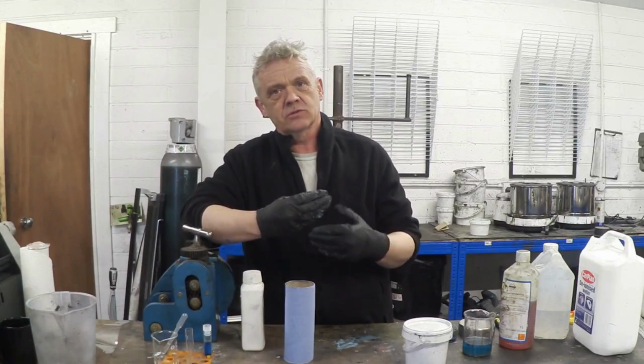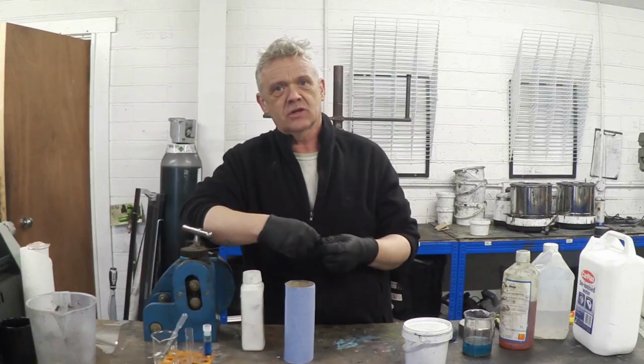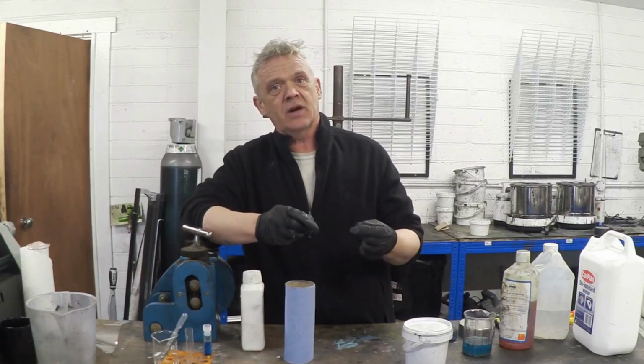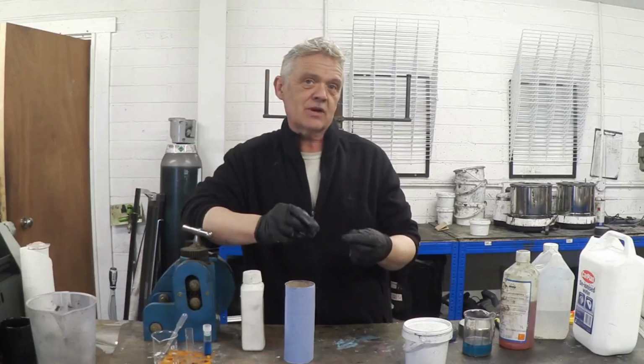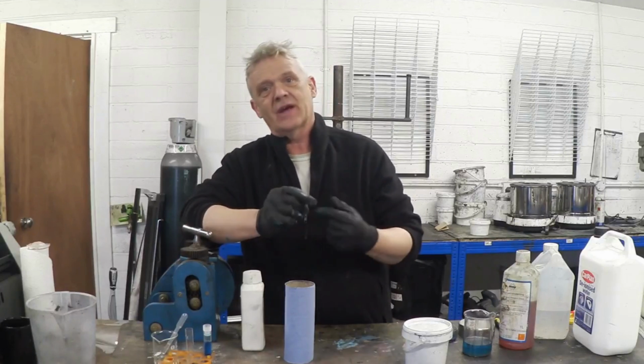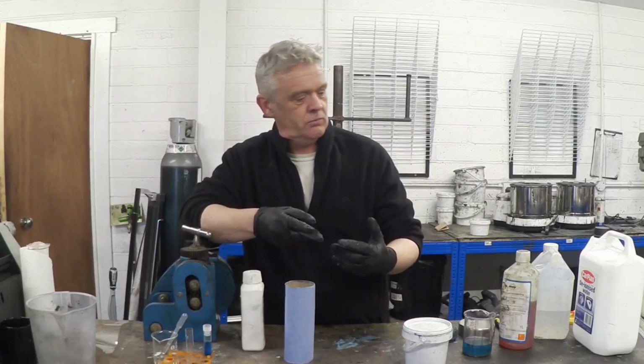Mix it with some graphite or some carbon, and then heat that to 200 degrees, and you'll form copper nanoparticles or copper nanorods within the graphite or within the carbon. And we'll do that as well and use that material.